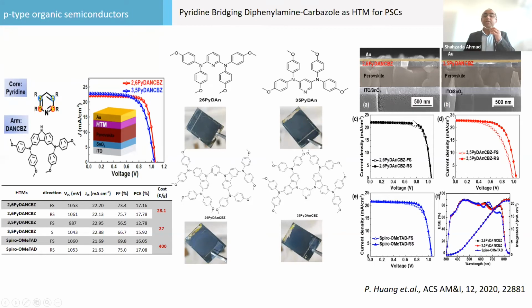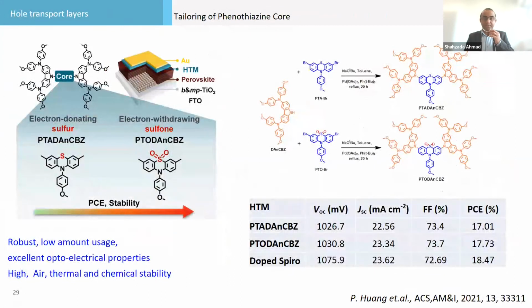So looking at the devices, 2.6 gives less hysteresis, 3.5 gives higher hysteresis, and even lower than the spiro, the hysteresis is almost negligible. It's just a cross section. You will see here that with almost 100 nanometer of HTM, we have less.